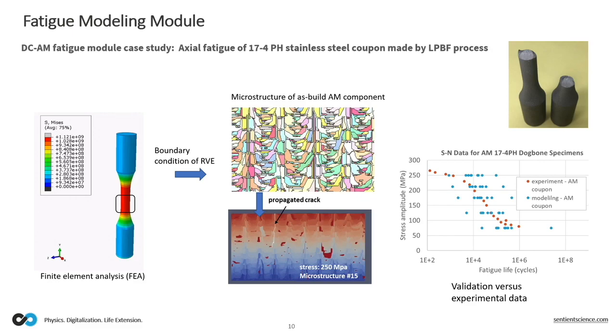And what you have to notice on the right-hand side image is that the prediction that we are making compared to the real data is pretty wide. And the reason for that one is that purposefully when we are doing the simulation, we are considering the worst case scenario to the best case scenario. In terms of fatigue, what that means, worst case scenario is when you have a bad flaw. You have a big inclusion, big void, and it happened that that bad flaw is also in the worst location that it could be, right under the load, right?